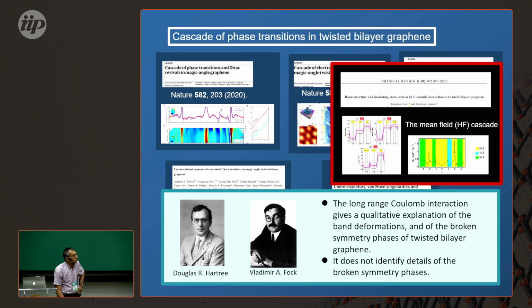then you will get to an atomic limit. So that's absolutely the case. But what I'm saying is that the flat bands, or the so-called flat bands of twisted bilayer graphene, are indeed very peculiar, and they are not, as Oscar is saying, at all similar to the bands people have studied in connection with strongly correlated systems, where everything is happening because there are well-defined localized orbitals, D or F or whatever.